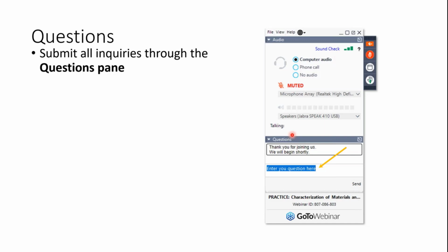So the first question that I have for you, June, is are the SEI layers as beam sensitive as lithium, or which one is more beam sensitive in the microscope? That's a great question. It depends how we define SEI. When it comes to dry SEI, when you fully remove excess liquid electrolyte, SEI is pretty beam tolerant. But if I were to compare the beam sensitivity between the lithium metal and SEI, I would say lithium dendrites are more beam sensitive.